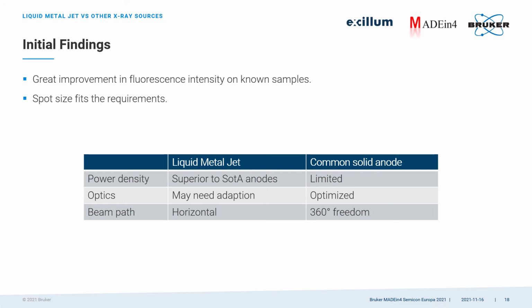This table summarizes our initial findings. The liquid MetalJet source shows a great improvement in fluorescence intensity compared to the common solid-state microfocus tubes on the same samples. Also, the spot size fits the requirements. The concept of the liquid anode is that the power load can be much higher compared to a solid-state anode. And this is beneficial because flux scales with the source power.